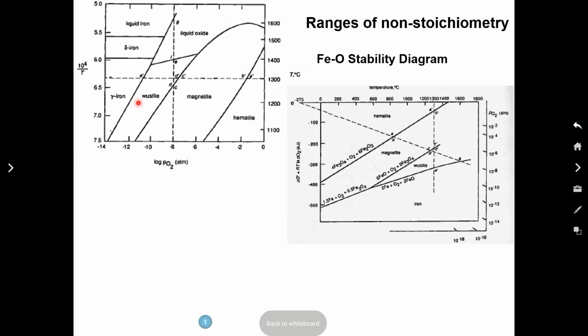So simply by the oxidation state of your iron, you're making different compounds that have completely different functional properties. And then on top of that, you can control the non-stoichiometry to fine-tune your functional property to a particular level. So that's the control. And the only knob that you're going to turn is your PO2. You do this at a given temperature and then dial PO2 to create different levels of non-stoichiometry.